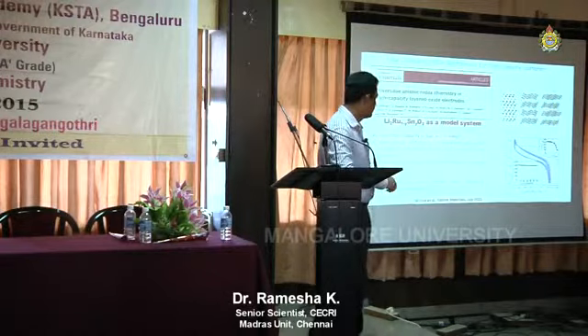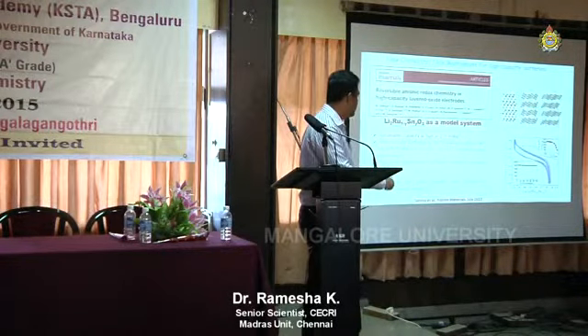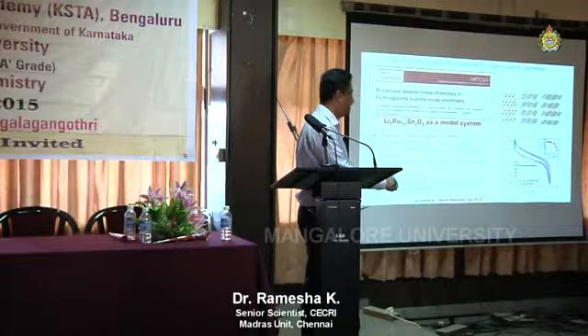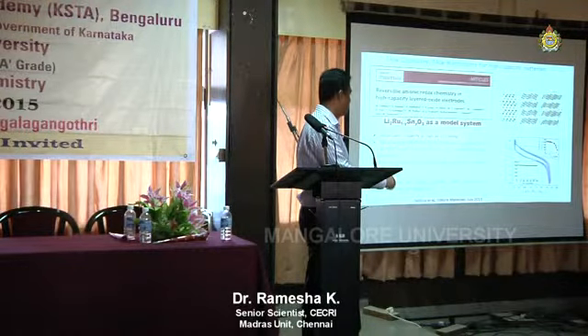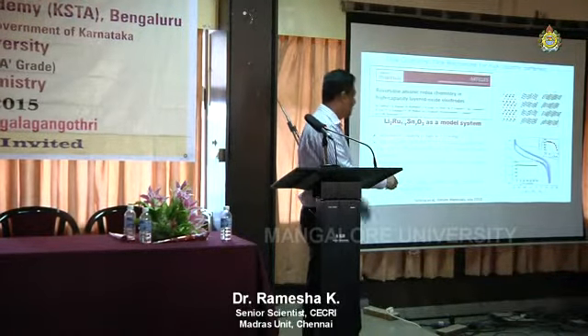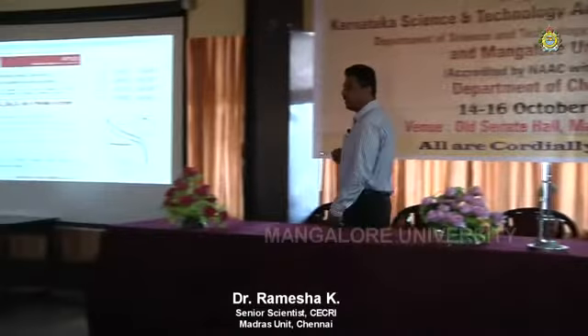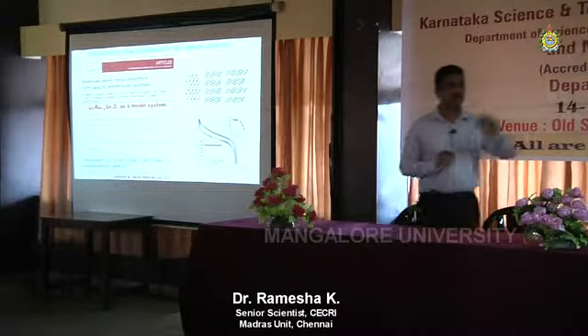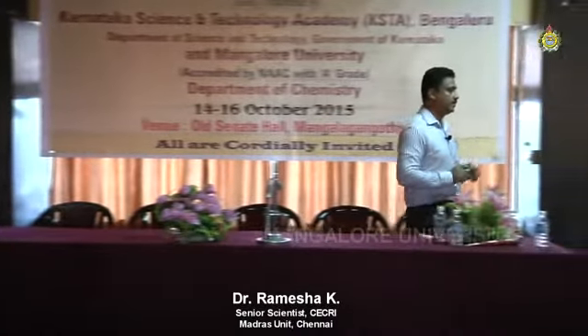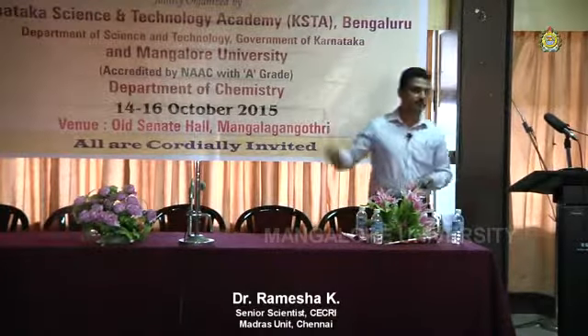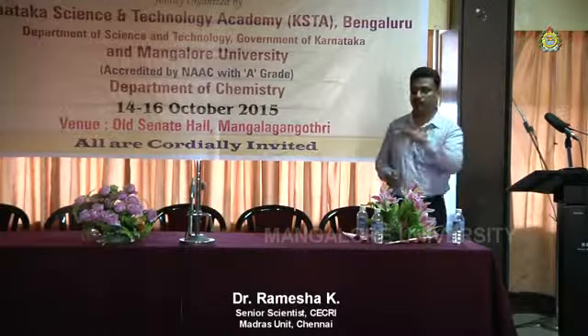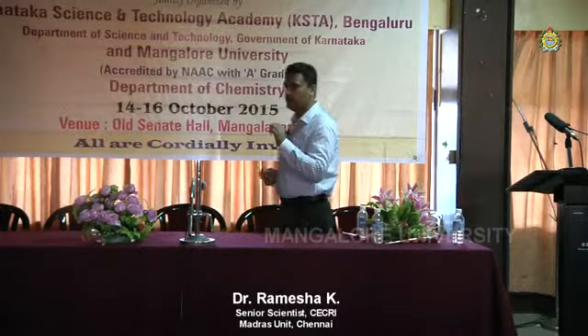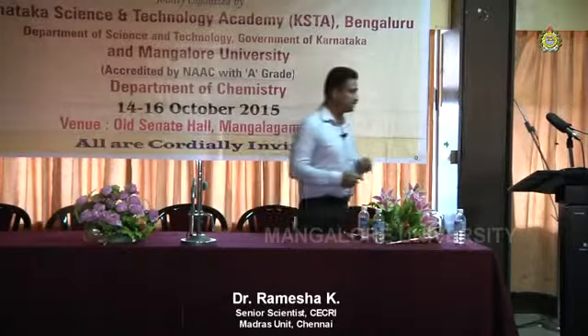Okay, next slide. So this is something related to that. We also put in a little bit of tin, and we show that here also the maximum capacity is doubled. By working on this, we also showed, see, in lithium cobalt oxide or any material, we say that there is a change in oxidation state of cobalt, right? 3 to 4 plus. But we never bother what happens to the oxygen or oxide. See, this is not gas oxygen, it is a solid. The oxygen is in the solid, in the crystal structure.